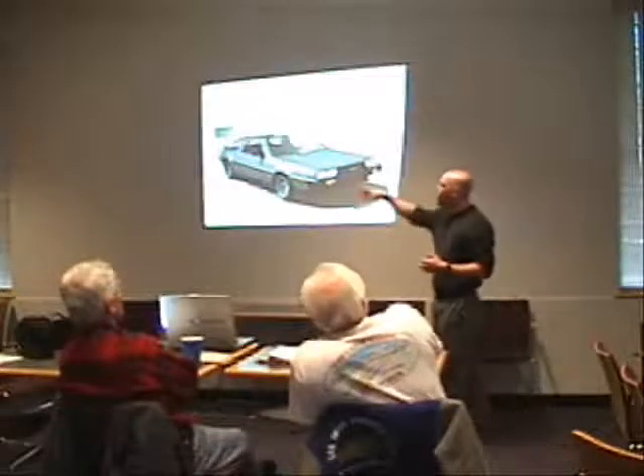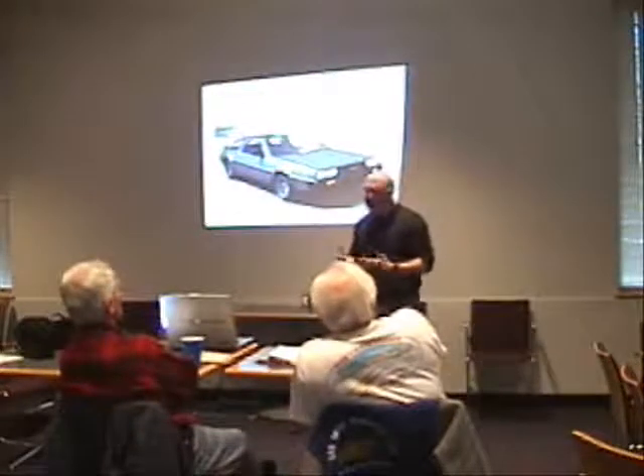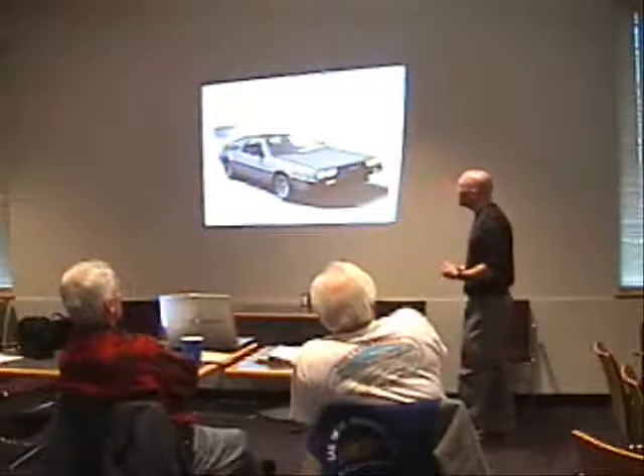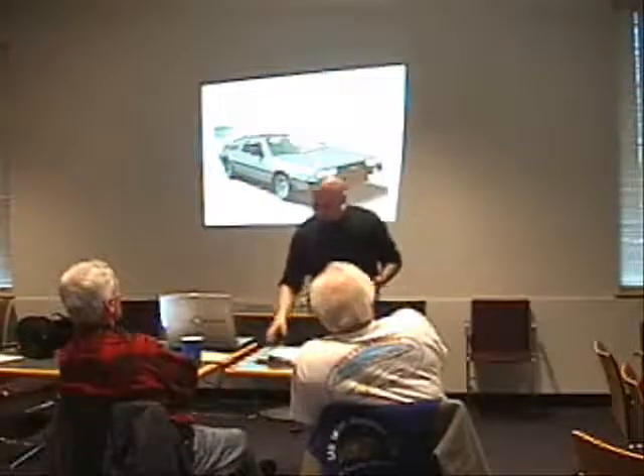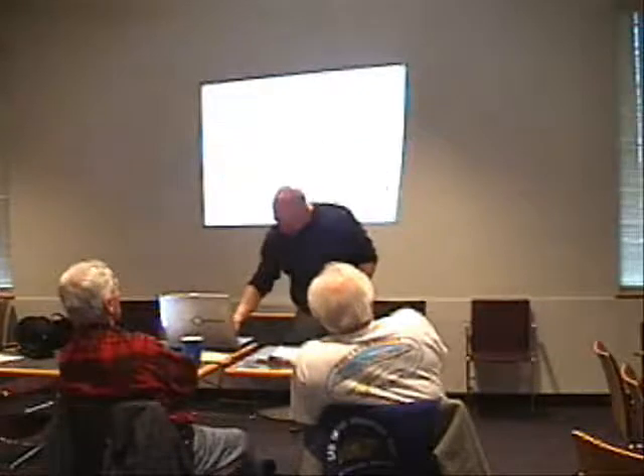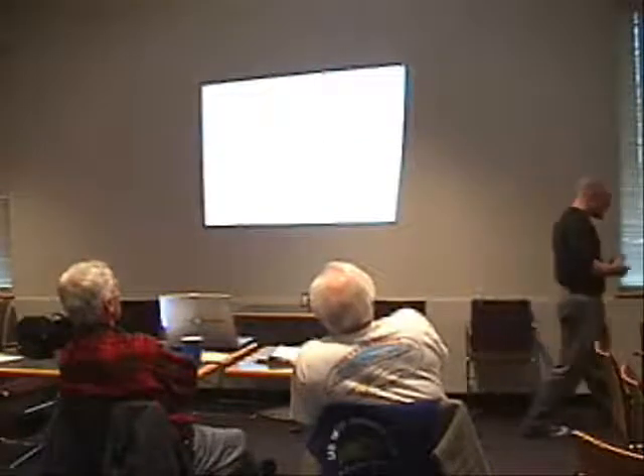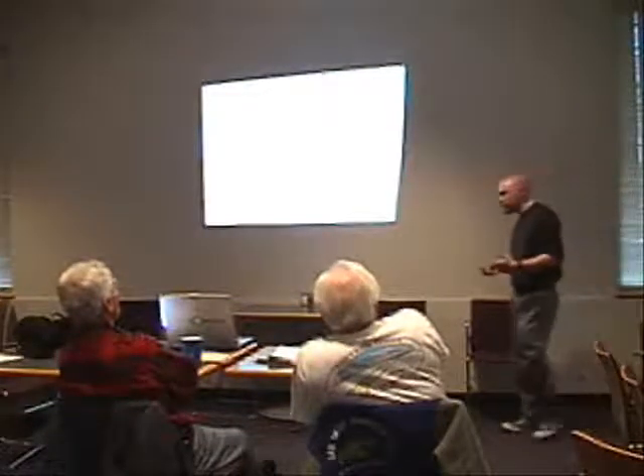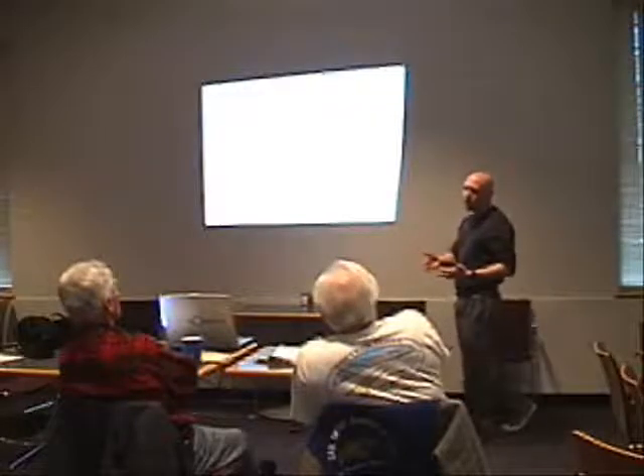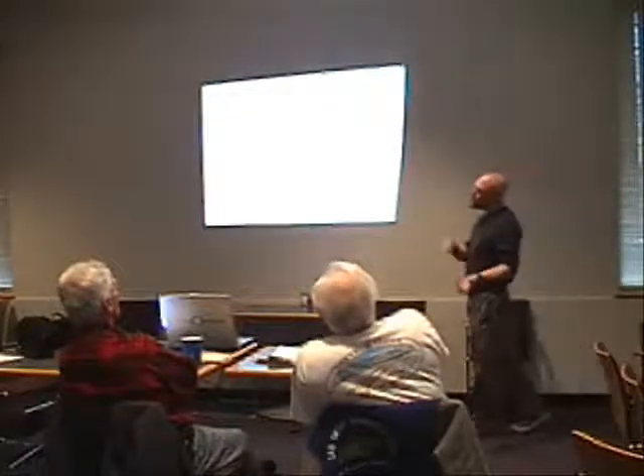They had all the required bumper sides, but it was hard enough. They really didn't expect too many dents and things as well. So this solution, if you will, was using an auto-passivating material, something that spontaneously forms an oxide on the surface. In stainless steels, it's the presence of chromium, which forms chrome oxide on the surface. In aluminum, it's aluminum oxide, Al2O3. Titanium, it's one of the titanium oxides, be it TiO or TiO2 or a suboxide mixture.